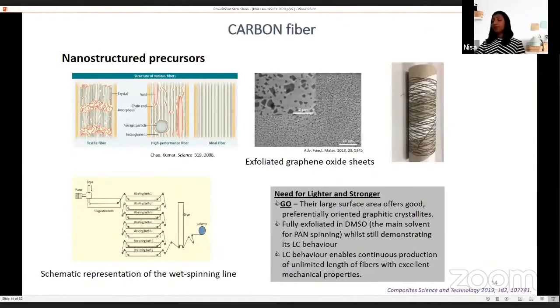Further in my research, our target was to make high performance fibers. An ideal fiber is one that will have very high strength, modulus, damage tolerance, and compressive properties. As you can see from the figure, the fiber will be free from all defects and impurities. Though carbon fibers are high strength materials, the mechanical strength of the current carbon fibers is limited by the presence of voids, defects and impurities in their fiber structure. Theoretically, it is estimated that carbon fibers can be made 10 times stronger than currently available fibers.